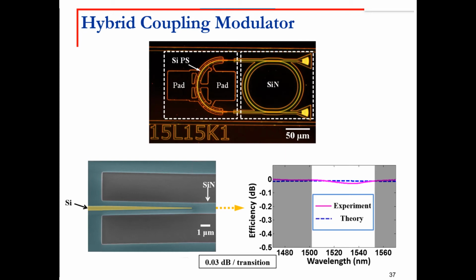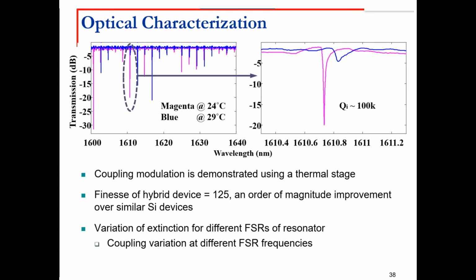This is the actual device that we fabricated. This is the resonator in nitride and the waveguide in silicon, with pads for applying the signal with PN junctions. And this is the response of the system. Just first to try the performance, we just heat it a little bit. Heating changes the index of refraction. By heating the device a little bit, we go from 0 transmission all the way to very high transmission. So that's the typical performance.